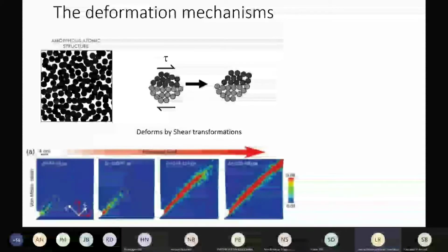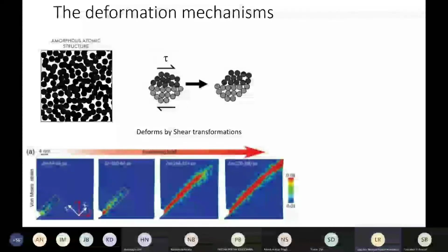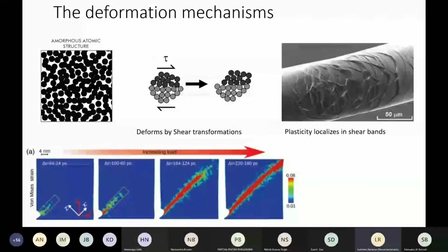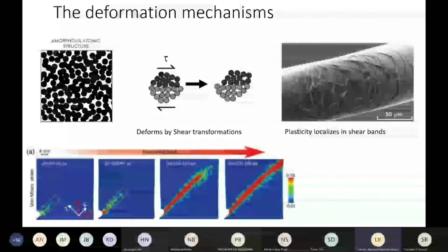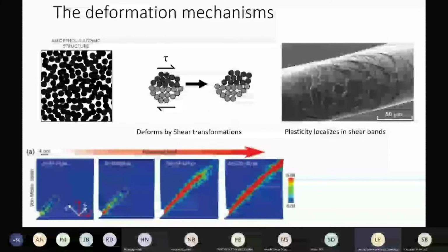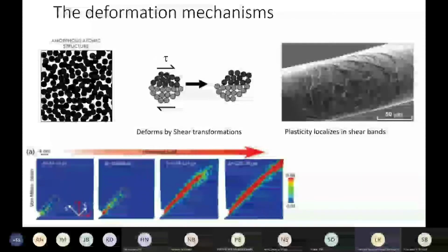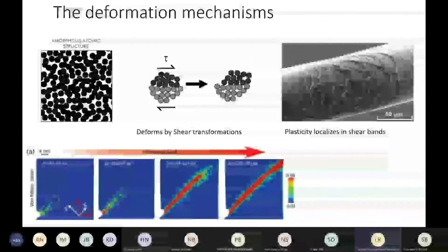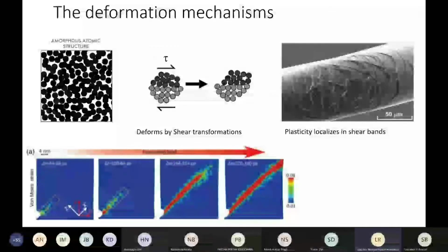Your shear transformation zones essentially join together inside the material one by one collectively and lead to the formation of a macroscopic shear band, which in reality looks like what you see in this picture. You will see a lot of these surface offsets, and this is a bent metallic glass pin. These surface offsets are nothing but representations of a macroscopic shear band. This implies that the complete plastic strain has localized in these shear bands, and the areas where the shear bands are not present are elastic or do not have any stress.